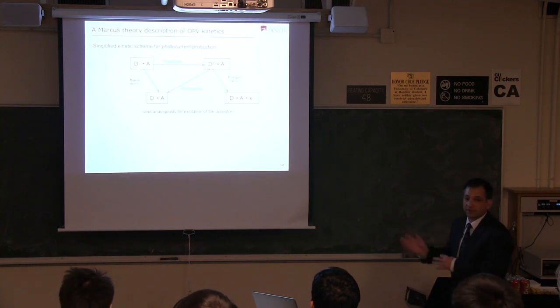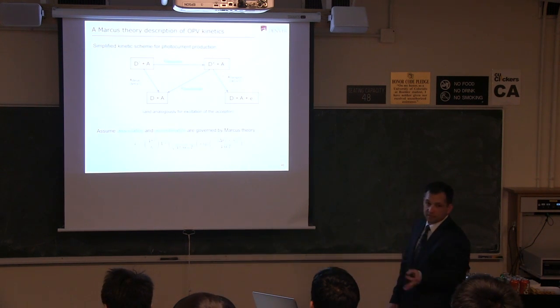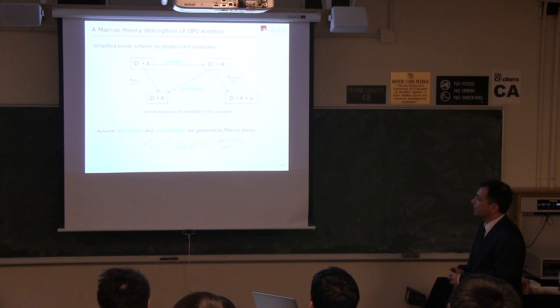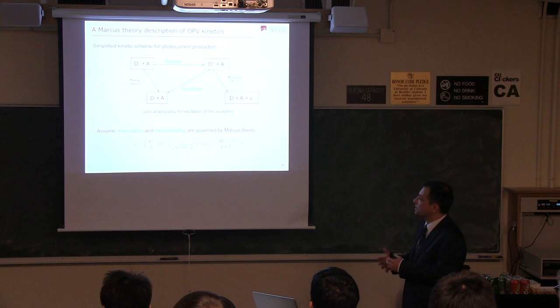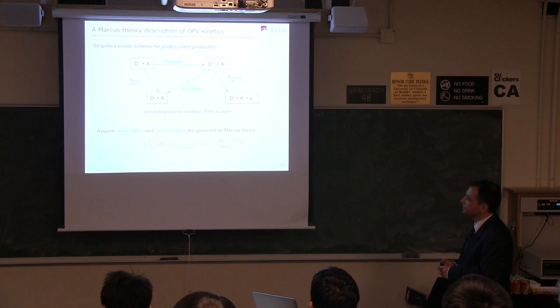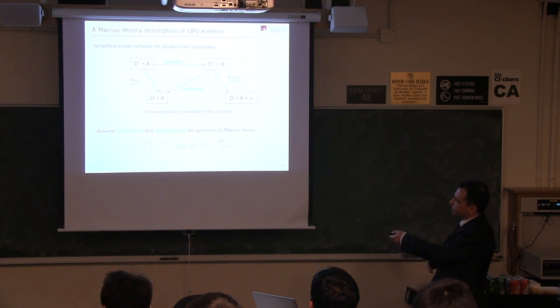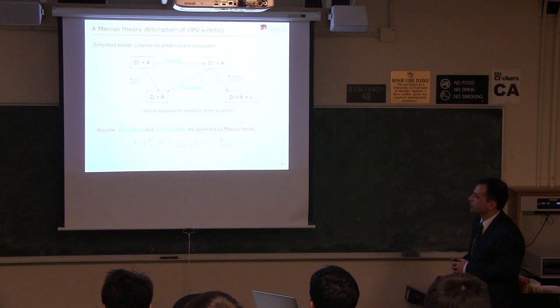So the ones that are determined by the energetics are this dissociation rate and that recombination rate. That's determined by the delta G's I just showed you. Now what's the equation that actually determines it? It's Marcus theory, Marcus electron transfer theory. This theory goes way back and is well understood, at least in chemical systems. And recently we've discovered that it works quite well in solid state organic semiconductors. Just to give you the highlights, there's the rate of reaction, there's the overlap integral between donor and acceptor, and it's squared. And then you have an exponential function of the free energy, or the Gibbs energy, delta G.